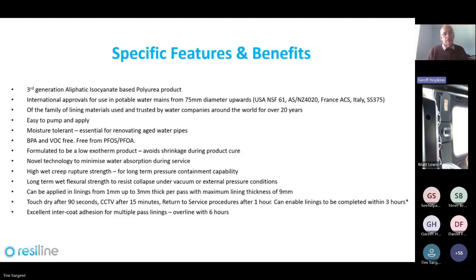This polyurea product is of a family of lining materials that's been used and trusted by water companies around the world for over 20 years. It's been developed to be easy to pump and apply. It's moisture tolerant, which we think is an essential requirement for renovating aged water pipelines. You're not in a factory environment here. You are always dealing with the potential of water ingress into what you're trying to line.